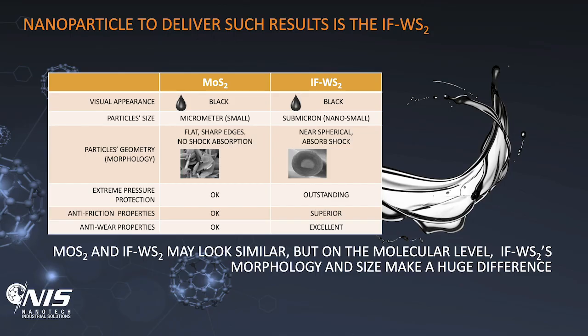So if we compare molybdenum disulfide and IF-WS2, the visual appearance is black because that's a natural material. They're different shape and different geometry. Extreme pressure for molybdenum disulfide is okay. It used to be outstanding. Right now the standards are different thanks to Nanotech Industrial Solutions. Right now, IF-WS2 is a new standard for extreme pressure, anti-wear, and anti-friction properties.